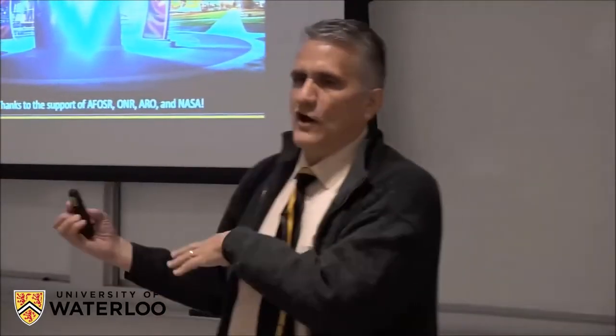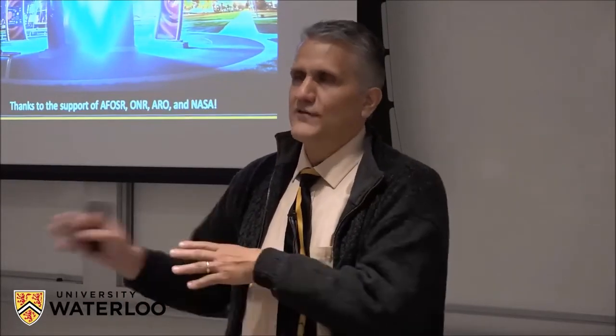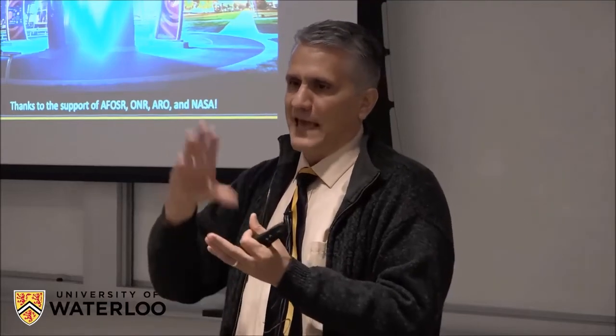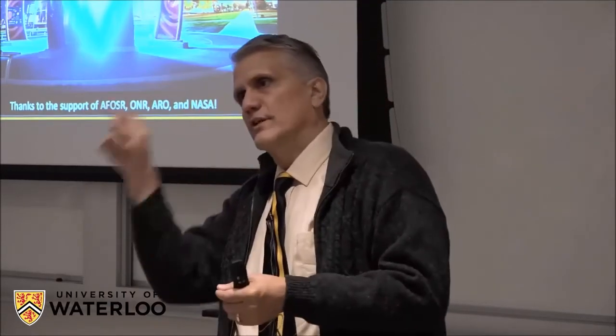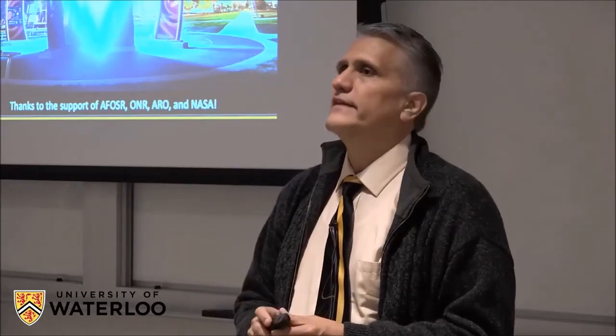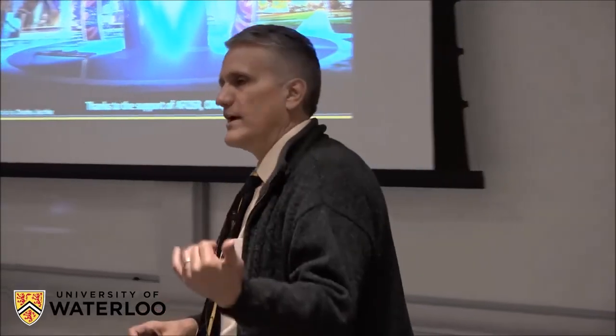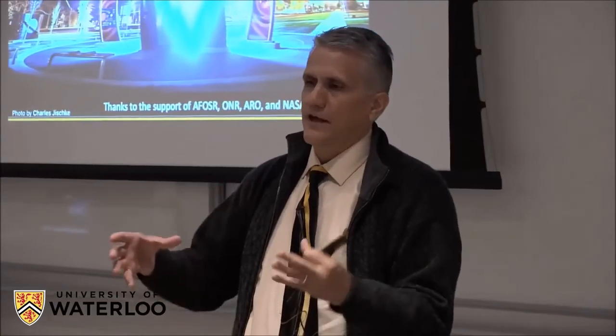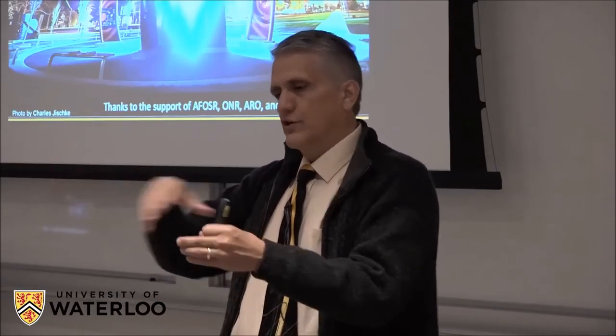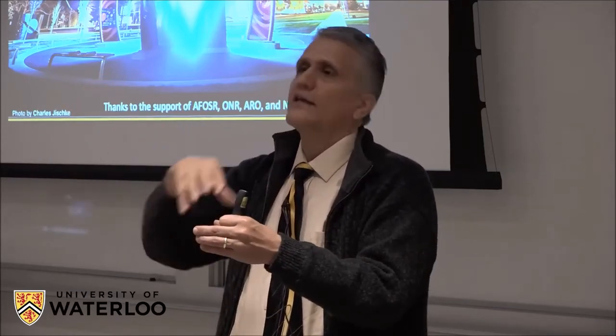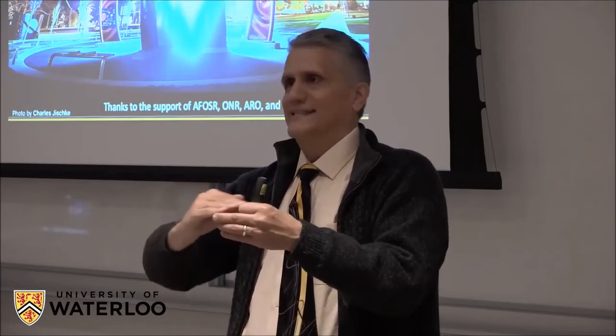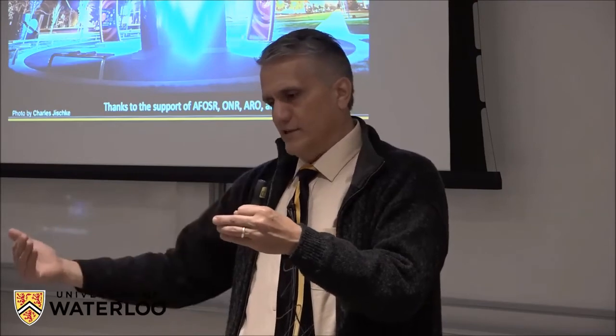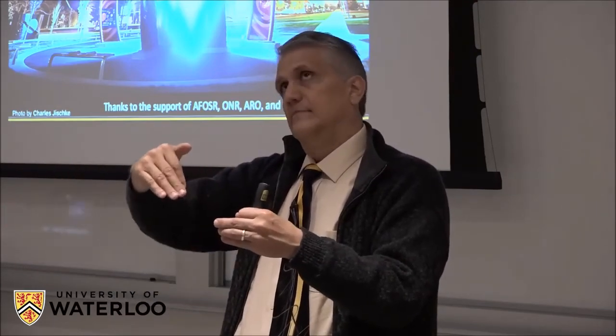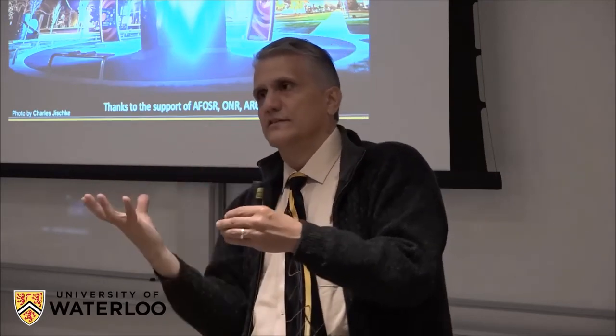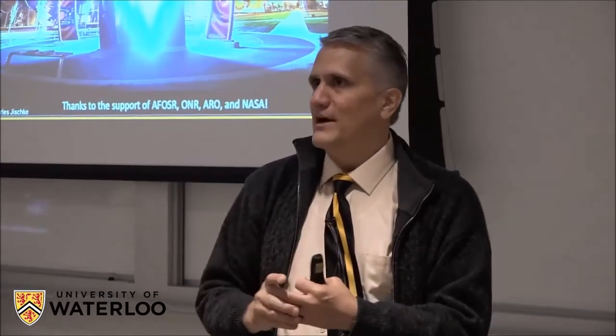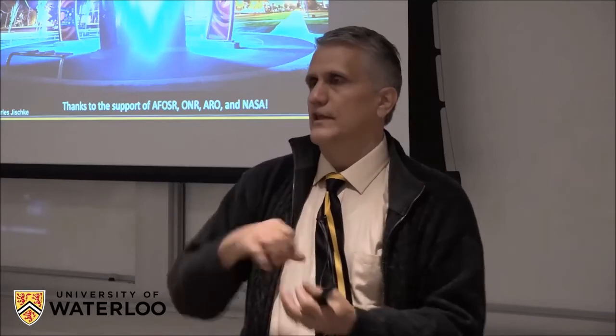For the FDM, my colleagues actually published a paper recently on not even energetic, but just FDM, and came up with all sorts of mechanical testing of quantifying: if you print different orientations, how does it affect the strength? So that's a real key issue that we need to look at. But there are ways. I was just this week talking to a colleague about UV cure: you put the polymer down and then you apply UV light, and that cross-links the polymer, and it makes that interface very problematic. There are ways you can bring in, I think he was saying you take an ionized gas and open up those links. So what I think going forward might be good to minimize those problems is to do that to improve the layer-to-layer adhesion.